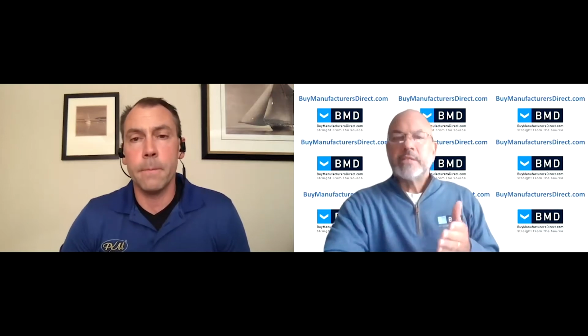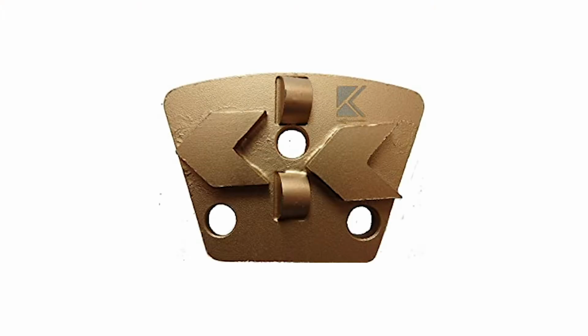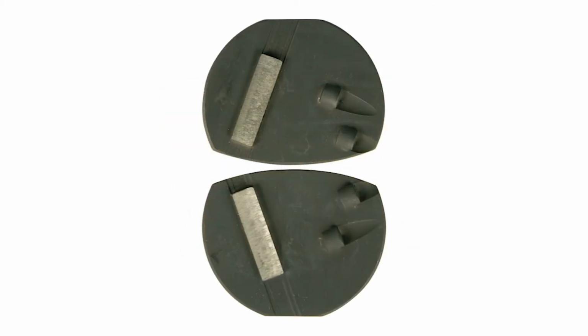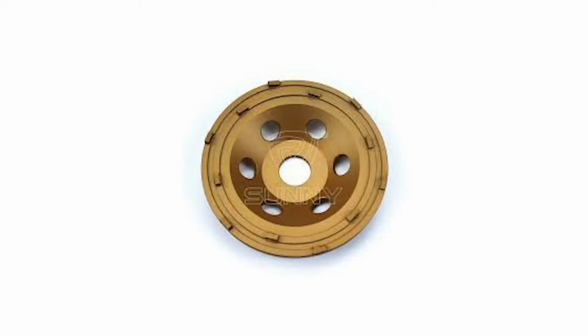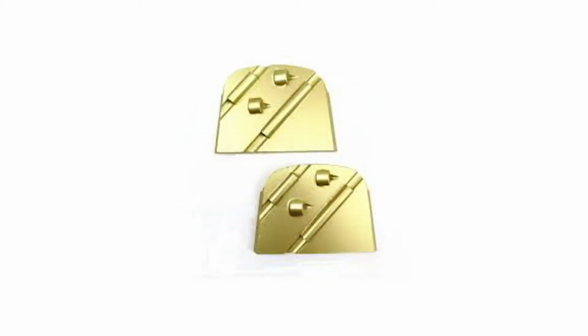So that begs the question, what is a more aggressive method of diamond grinding? Well, you can do diamond grinding with PCDs. Now, PCDs are a little bit different animal, but it still runs on the same machine. It still runs laterally across the surface of the concrete. But the difference with a PCD is it actually has chips or chunks of carbide that has PCD, polycrystalline diamond, on the face of that holder that drags along and literally gouges the surface. So it's usually going to be more productive than a diamond, which is a small chip. PCD is literally a chunk, so it gouges away at the surface of the concrete.